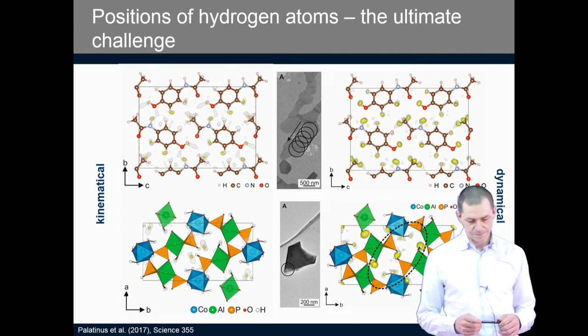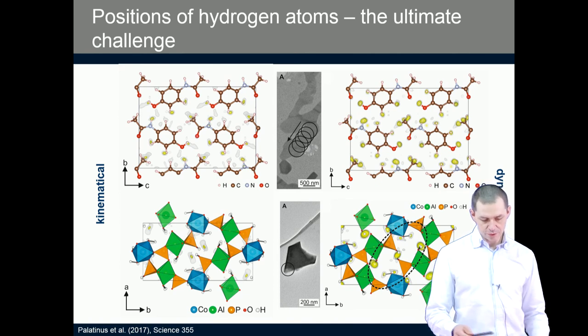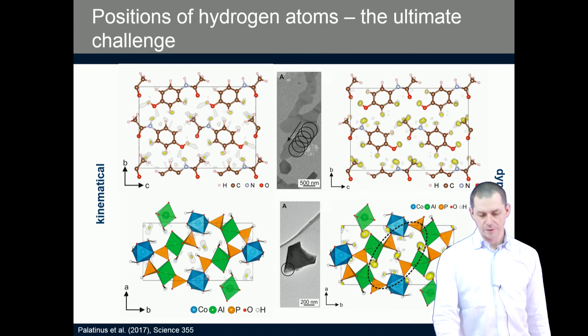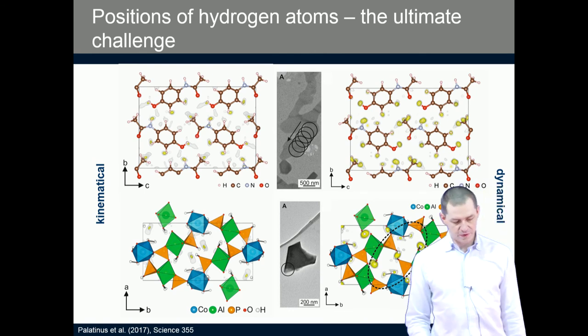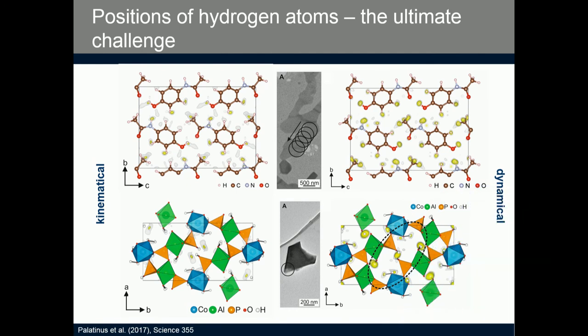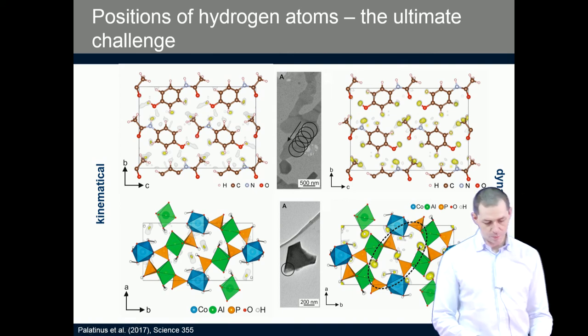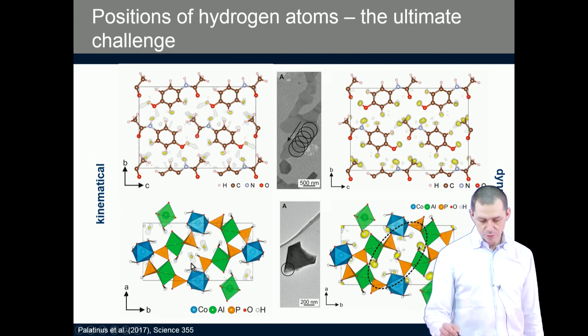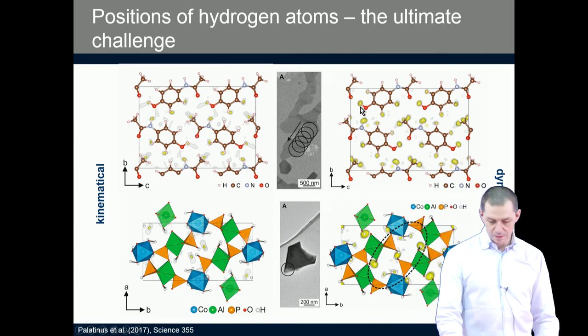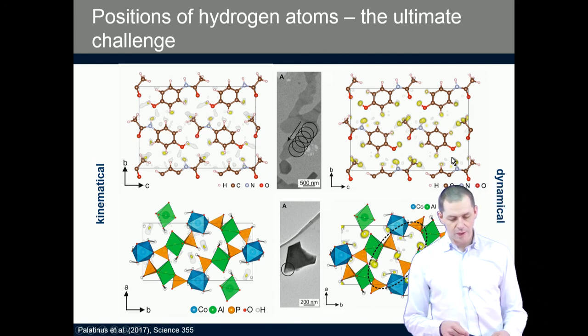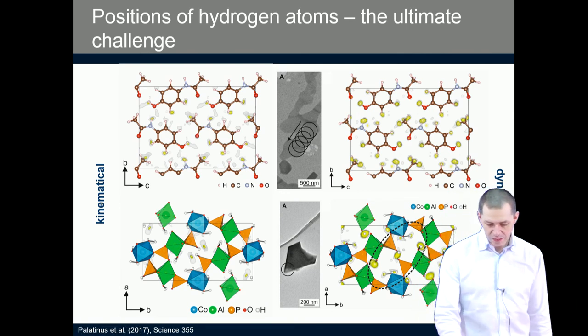These are the two cases that we showed used as a first demonstration: the structure of paracetamol, an organic painkiller drug, and the structure of cobalt aluminophosphate, which is an inorganic framework material. In the center you see the crystals that were used for the data collection. On the left, you see the result of the kinematical refinement, where there are a few possible positions of hydrogen atoms visible in the paracetamol case, but not a hint of good hydrogen position for the cobalt aluminophosphate. On the right hand side, you see that if we do the dynamical refinement, the positions of hydrogen atoms are all clearly located in the difference Fourier map, and they are all above the noise level.